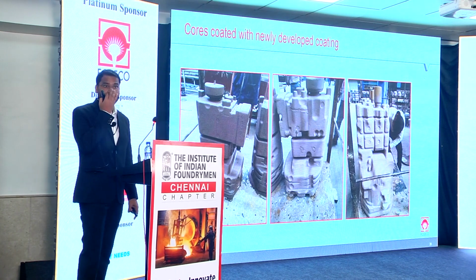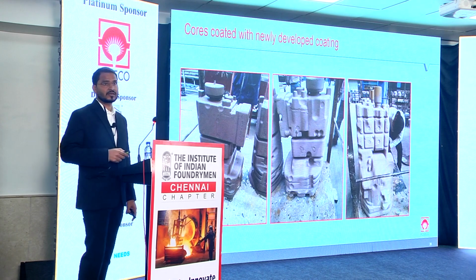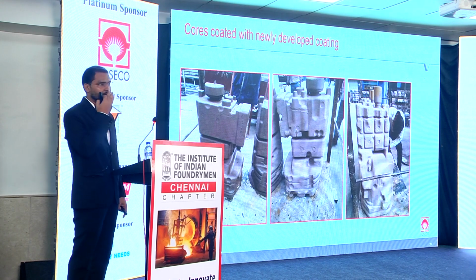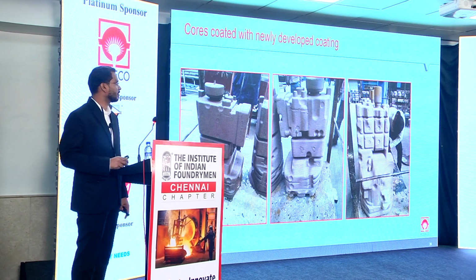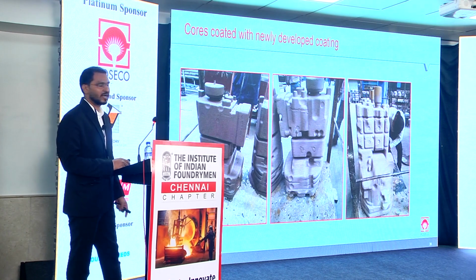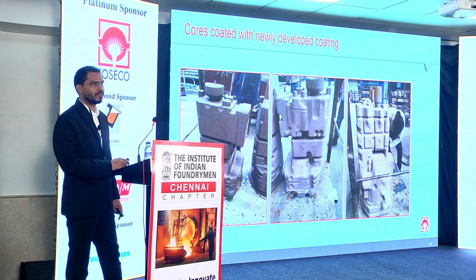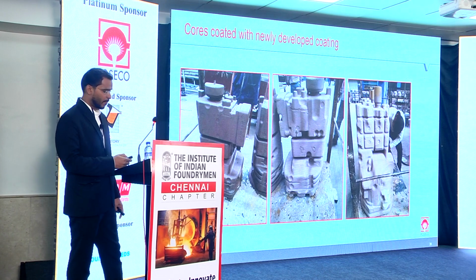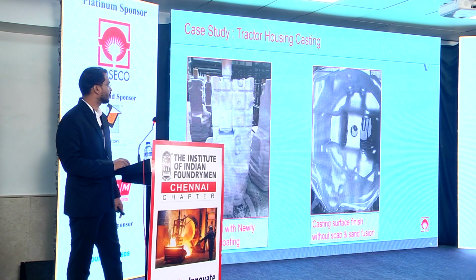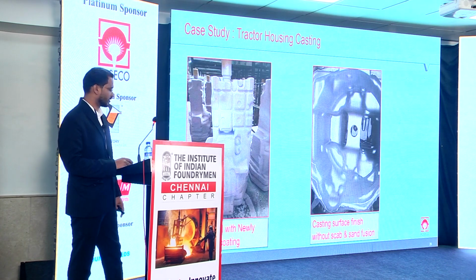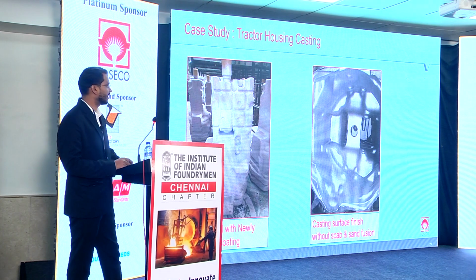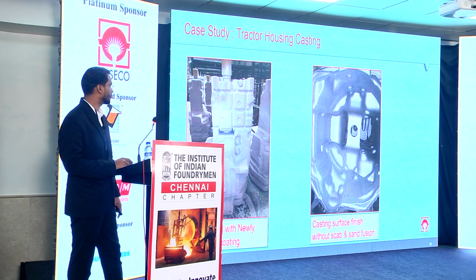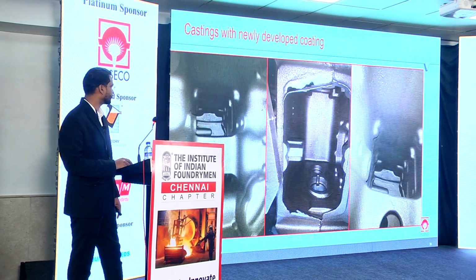The foundry has large tanks of 3 metric tons and 2 metric tons, and these cores are coated with robotic dipping applications at a viscosity of 15 to 16 seconds, maintaining 250 to 300 microns of build-up, and then the castings you see are clean castings without any scab, as well as very clear internal passages also. No sand fusion, no scab.